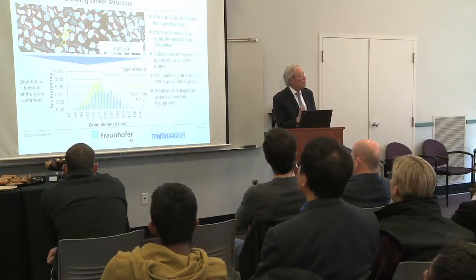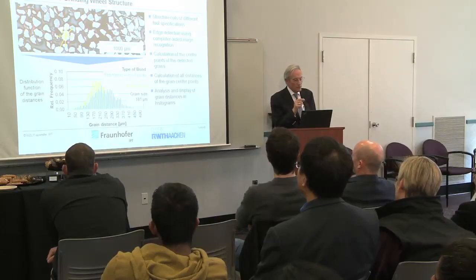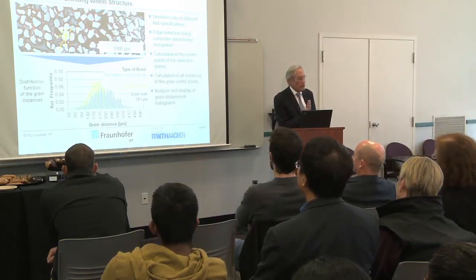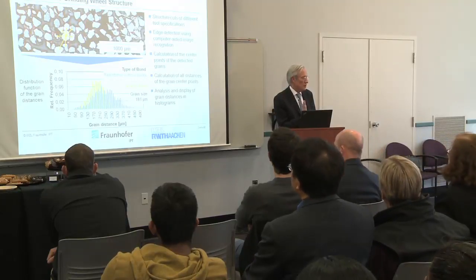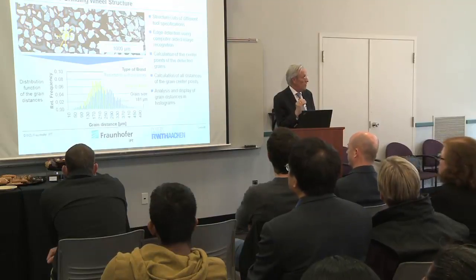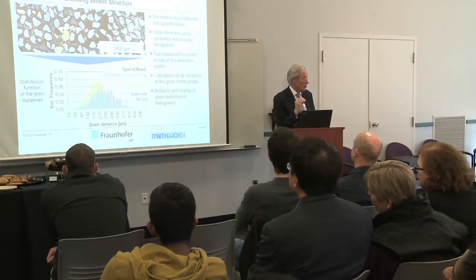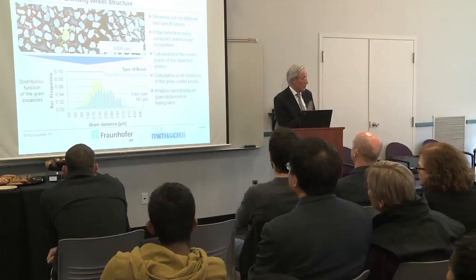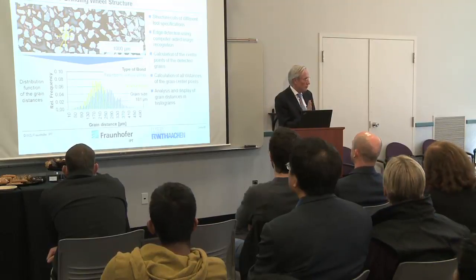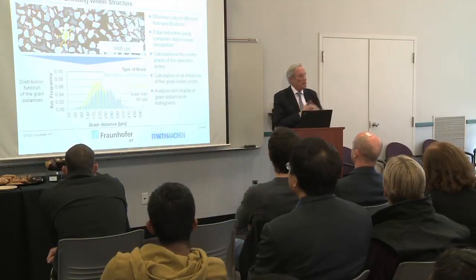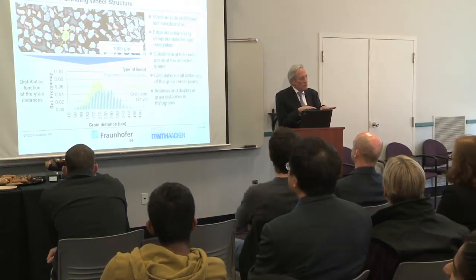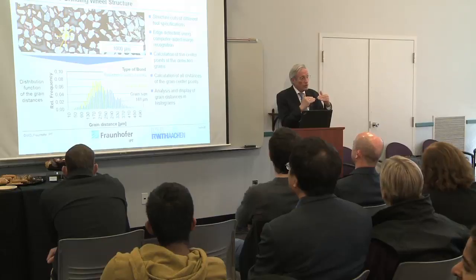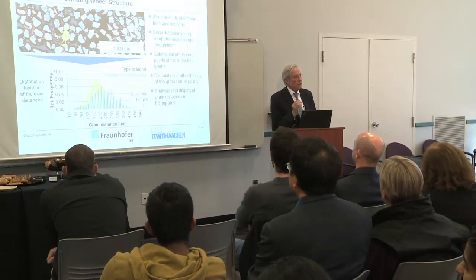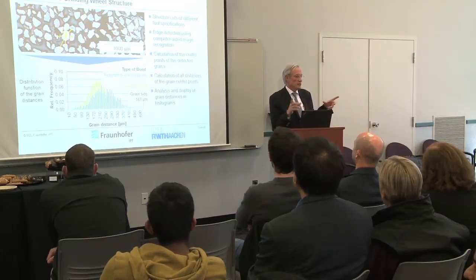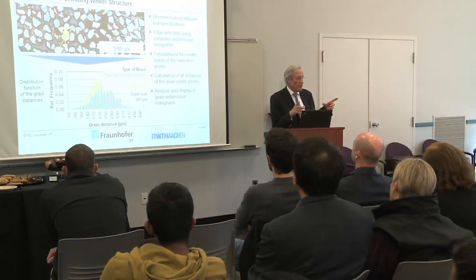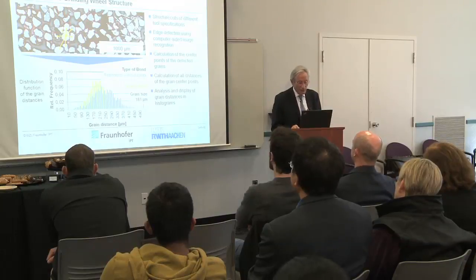So what we see here now, the slide might be a little bit busy, but if you look carefully, you see these yellow bars, which represent ceramic bonds. And you see the blue bars, which obviously don't fit 100% to the yellow bars. So there's a shift in between. And the only influence here is the making. It's a grinding process. That was a phenolic bond or an epoxy bond compared to ceramics. And if you process a phenolic bond, you do it with heat and pressure at the same time. And then you have high viscosity, and then also the grains start to move, and you also change volume. At the bottom line, you get a wheel where, despite the fact that the number of grains was exactly the same, the distance between the grains is different. And if that is the case, you have different grinding behavior.